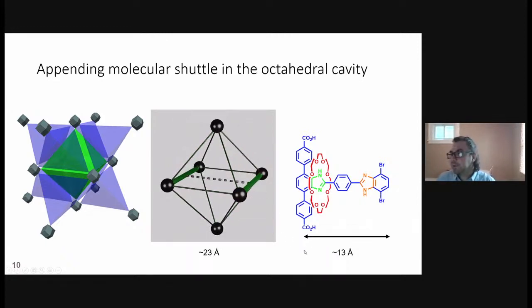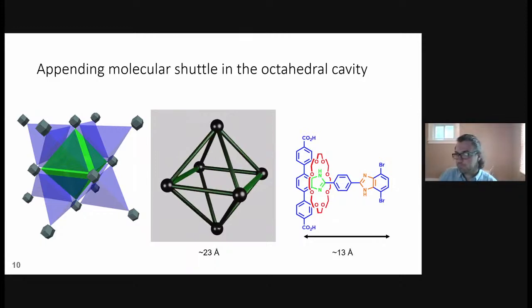Instead, we decided to make things a little bit easier for ourselves, and we simply appended this 2-rotaxane molecular shuttle onto this linear dicarboxylate here. And the reason why we chose this approach is this rotaxane protrudes about 13 angstroms, so it will fit in the octahedral cavity, but it's too big to fit in the tetrahedral cavity, so we can still control the position of the rotaxane in the MOF.